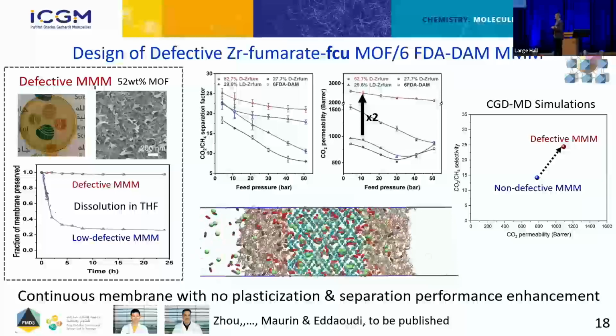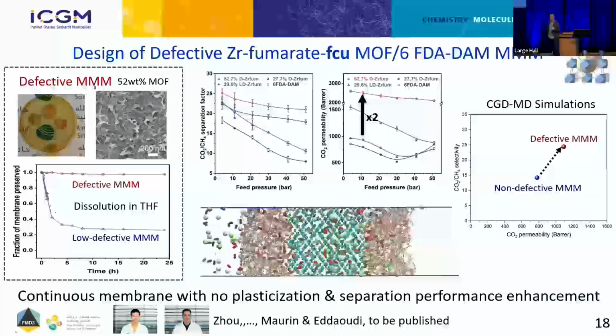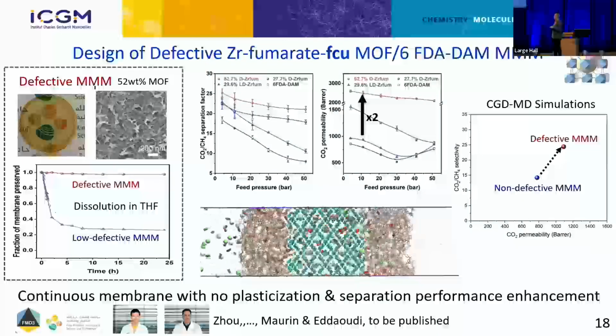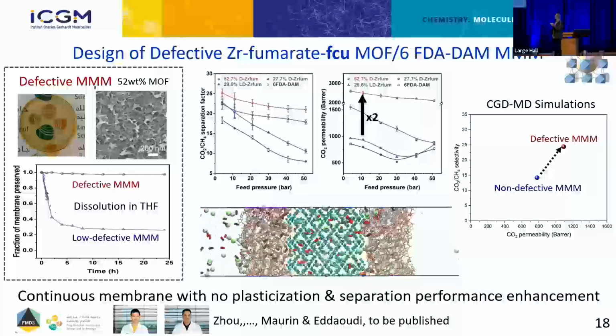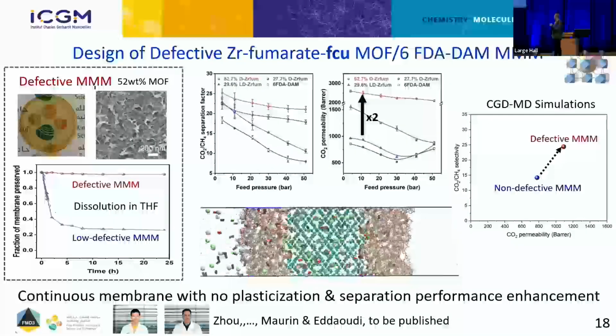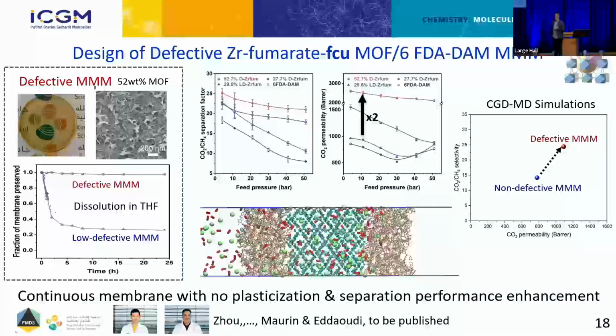Okay, then here, in our non-equilibrium molecular dynamics simulation, we're interested in understanding the diffusion of CO2 and CH4 in this system. What we have found, in this graph, where we report the CO2/CH4 selectivity versus the CO2 permeability, is an increase of about a factor of 1.5 for the permeability, while the selectivity is relatively even improved in the case of the defective polymer.